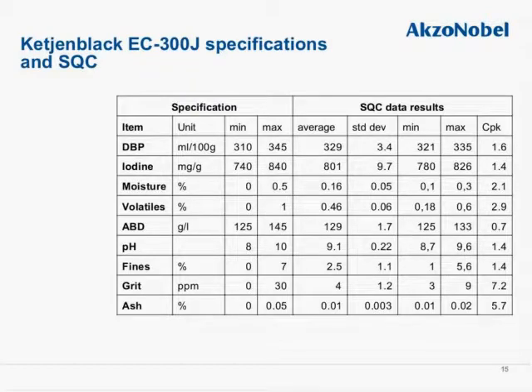Specification of Ketjenblack EC-300J, we have a number of quality control tests that we run, and all these products are reported on the certificate of analysis in terms of surface and moisture content, volatility, density, bulk density, pH, very important, fines, grit, and ash. The fines are one of the lowest that you will encounter in terms of this kind of conductive black. For us, maximum is about 7%. That means 93% of the product is going to be in a pelletized form.